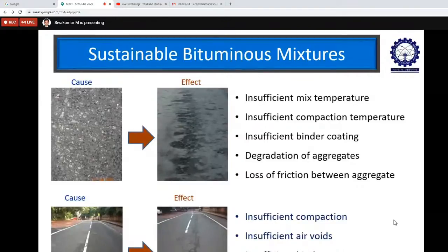Because the temperature is low, insufficient binder coating will be there, so the aggregate will not be fully covered by the bitumen binder. In the left-hand picture, you can see more white patches, that is, without coating. Then what will happen is, in the first monsoon itself, these aggregates may degrade. It will come out as raveling, stripping as well as raveling, and then degradation of aggregates may take place. Because of insufficient binder coating, there may be a loss of friction between the aggregates.